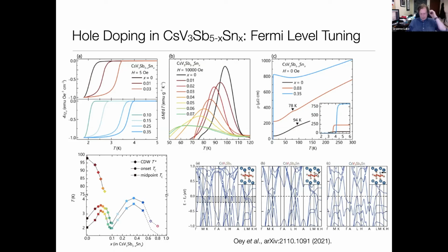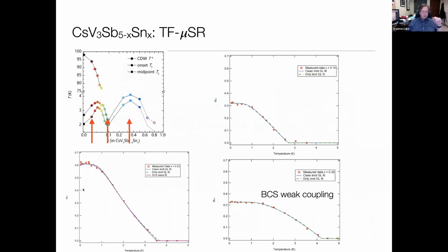So we started to look at these materials to see how we still have a bulk superconductor. You see very good flux expulsion. It's still 100% for all of these samples, and to see how the nature of the superconducting state is going across the phase diagram. So we took a series of three doped samples.